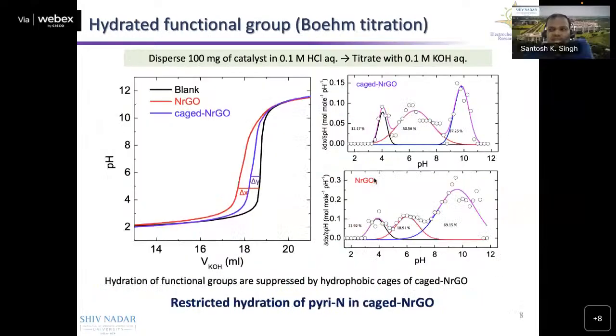As I told in the initial time itself, there are three kinds of nitrogen: pyridinic, pyrrolic, and graphitic. It is already proven that pyridinic nitrogen is highly responsible for the higher activity. Most of the catalysts being developed nowadays have a higher amount of pyridinic nitrogen, but the pK value of this pyridinic, pyrrolic, or graphitic nitrogen is responsible for the change in the activity. So it will apply in all the cases, even if you are developing a catalyst having functional groups like COH or OH, which are responsible for the change in the activity. In that case also, pK is the most important criterion for getting higher activity.